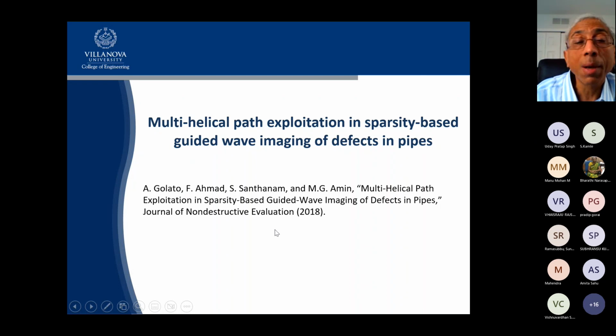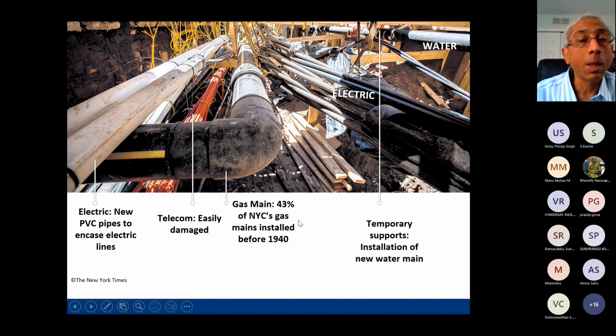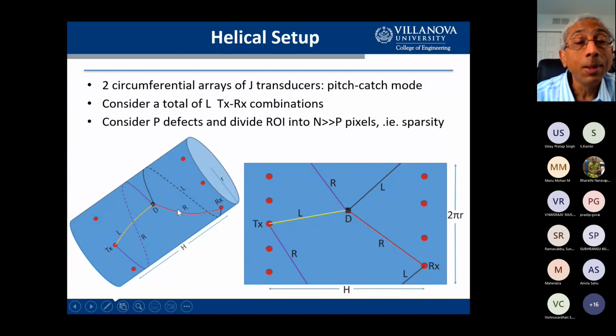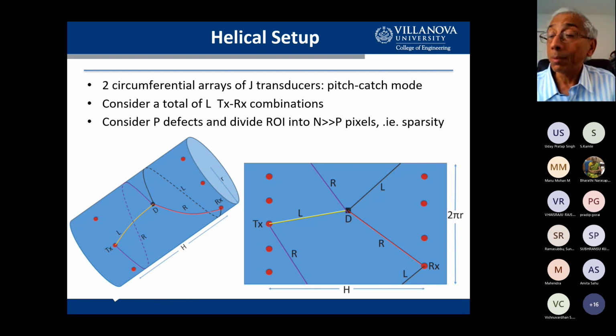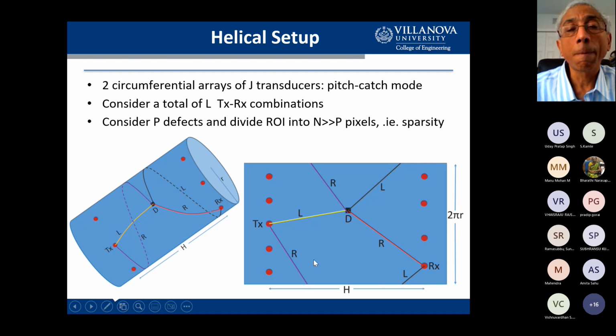So we've done the same multi-path modeling here. This time the paths are a little more complicated. They tend to be helical because you don't have a pathway straight from one location to another location in a plane. You're going to go around the surface of the tube, the pipe, as you develop your paths for the waves. But fundamentally, it's the same idea. And so you get all kinds of pipes, and again, the paths are all helical. Right-handed helix, left-handed helix. So the R stands for right-handed helix, L stands for left-handed helix. You can take the cylindrical surface and unwrap it and make it rectangular or flat. And so then you can take the ideas that you develop for a flat plate, and apply it to a cylindrical pipe as well. And the details you can find in one of the papers that we published.